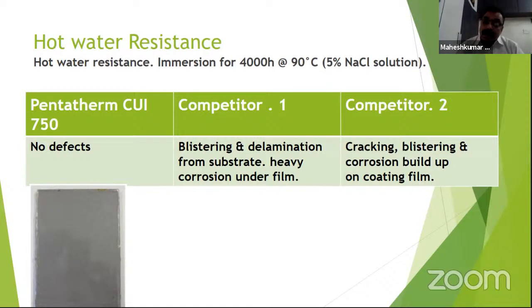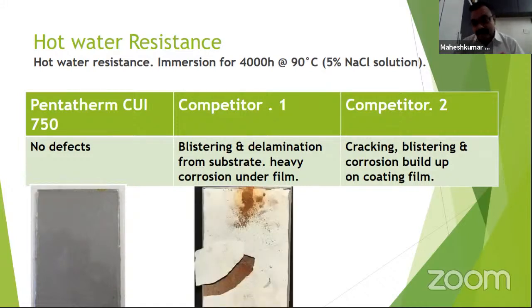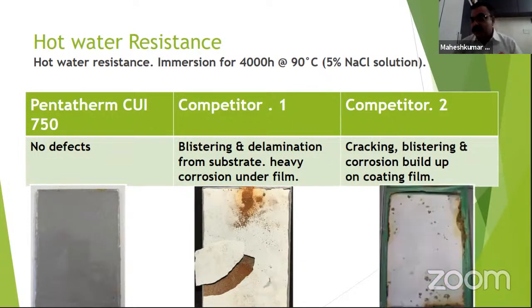We almost replaced our water, refilled our water more than 600 times, because it was going all out of the system. I don't believe this particular test, because most of the time it was showing that there is delamination taking place in both the competitors, because there were blisters occurring. So I retested it once again, in a separate manner, and the results were absolutely the same.